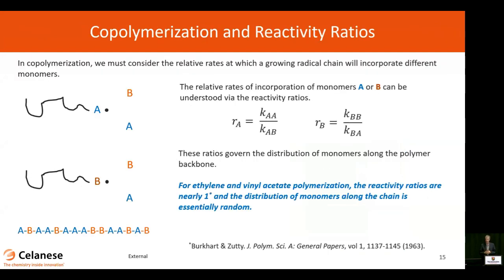Okay. So last piece on copolymers, there was a very nice talk earlier about the effects of copolymerization in PLGA and how you have to deal with the reaction kinetics of PLGA polymerization. With EVA, the story is actually quite simple, right? When we talk about a copolymer, we always think about the reactivity ratios. The reactivity ratios tell us something about the likely blockiness of the polymer that we're going to achieve. One of the nice things about EVA is that for the polymerization of ethylene and vinyl acetate via free radical polymerization, the reactivity ratios are very, very close to 1. So you have something that's almost exactly a random copolymer. So from the standpoint of characterizing blockiness, or the relationship between molecular weight and the copolymer content, those should be fairly uniform across the polymer. It's just baked into the chemistry.